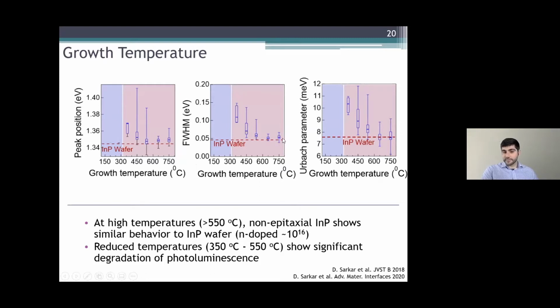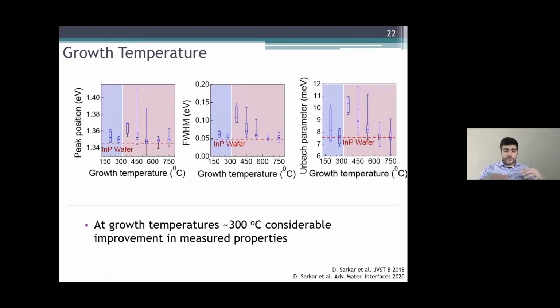The full width half maximum is again pretty close to what you get from an indium phosphide wafer. Our Urbach tail parameter is pretty good. But as you start to get lower and lower in temperature, closer to the holy grail of 400 degrees C, you get this divergence and the properties seem to get significantly worse. So that's not promising.